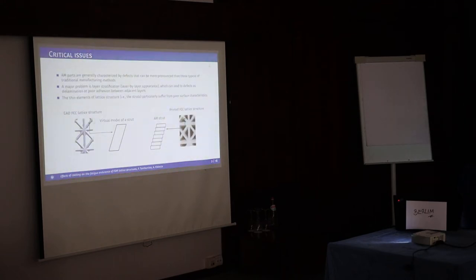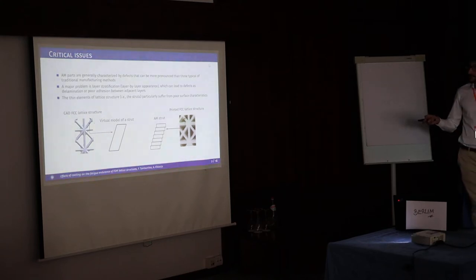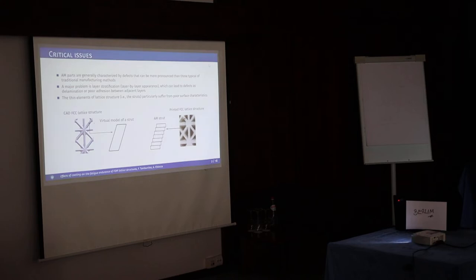Focusing on the topic, we're speaking about FDM printing, additive manufacturing, and lattice structures - specifically FCC lattice structures. The main problem with printing lattice structures is the different geometry we get, especially for small components. When struts are really small, millimeters in this case, FDM printers can have problems printing the nominal geometry. We can easily obtain staircase geometries that can give problems from delamination to adhesion issues.